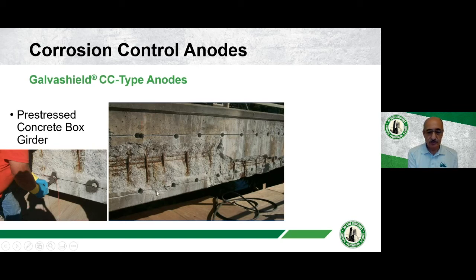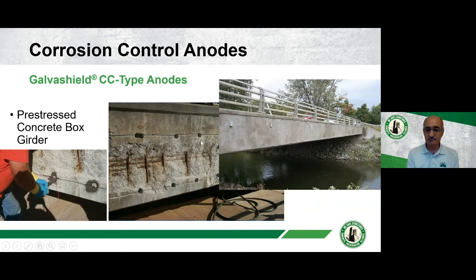In this case, it's just 2 lines of anodes that were embedded to protect the central region of that. One advantage of using galvanic anodes in pre-stressed steel or post-tensioned is that without having to worry about it, you're ensuring that your steel doesn't get down to potentials where hydrogen evolution would occur, because the natural potential of the zinc is such that it doesn't do that. So you get safe protection. Okay, that's the after effect, if you like. That's what it looks like.